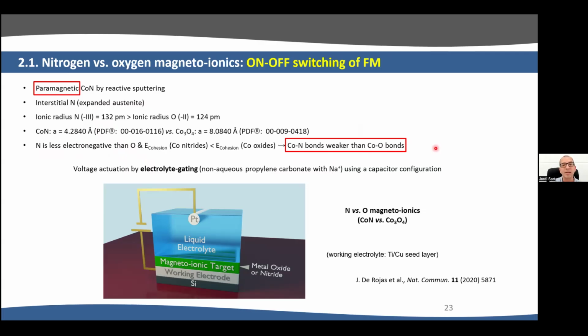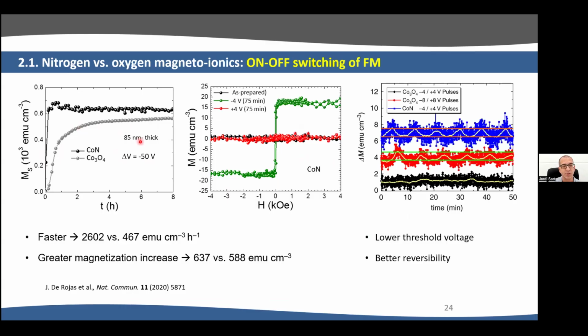We tried to see what happens in cobalt nitride if we compare cobalt oxide and cobalt nitride of the same thickness. In our case here, as I'm showing, it's 85 nanometers. And this is how the saturation magnetization increases as a function of time. You can see for cobalt oxide that when we apply voltage here at the instant zero, the magnetization starts to increase, and it increases even for several hours. After 3-4 hours, it's still increasing. However, for cobalt nitride, everything happens in the first minutes. So cobalt nitride is indeed faster than cobalt oxide.